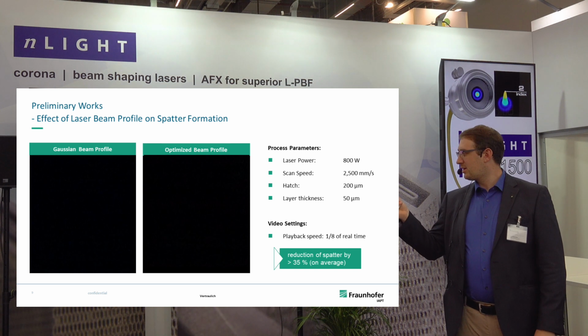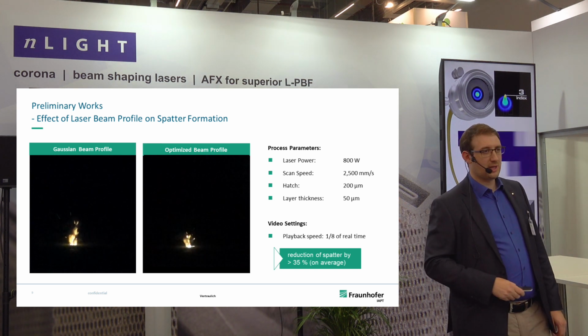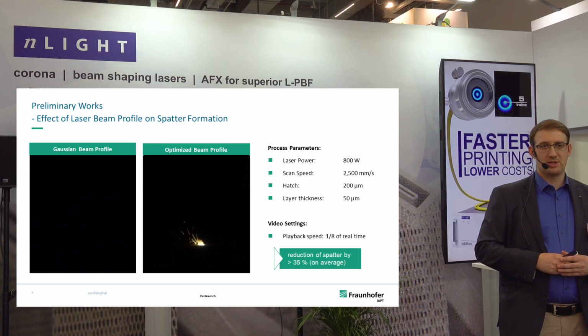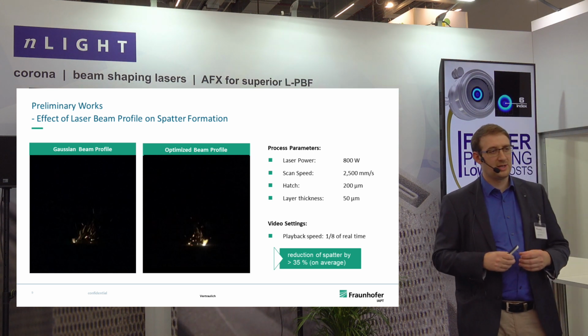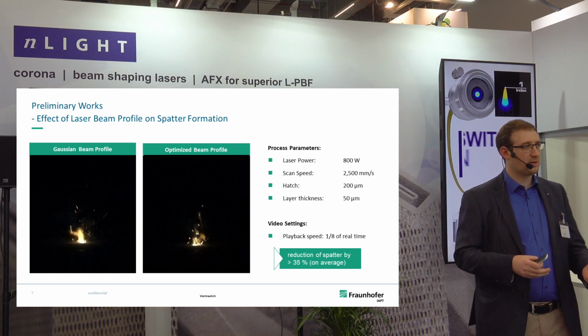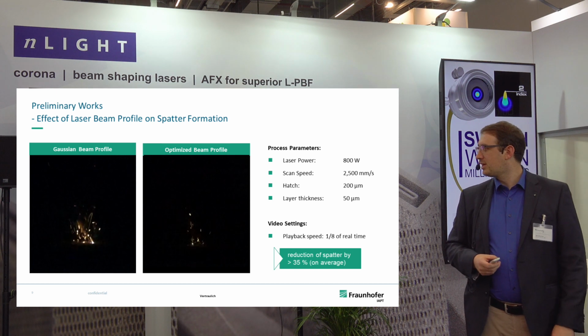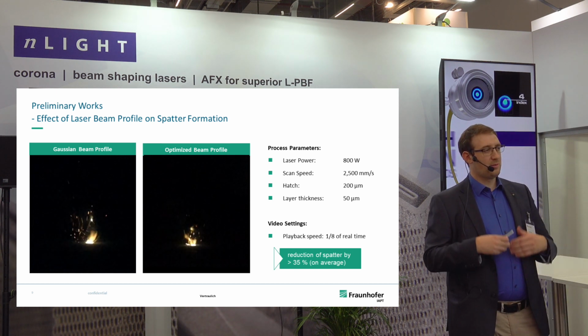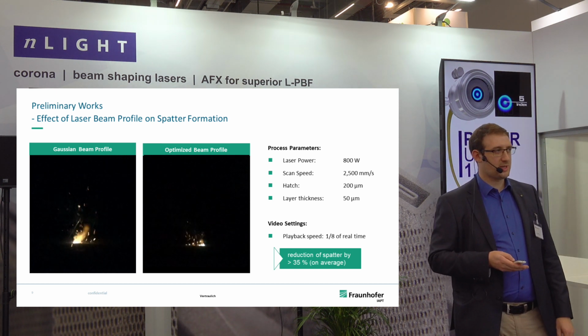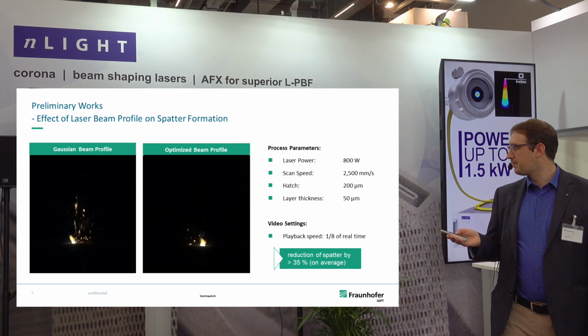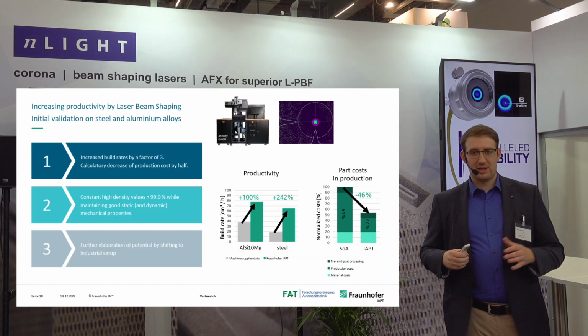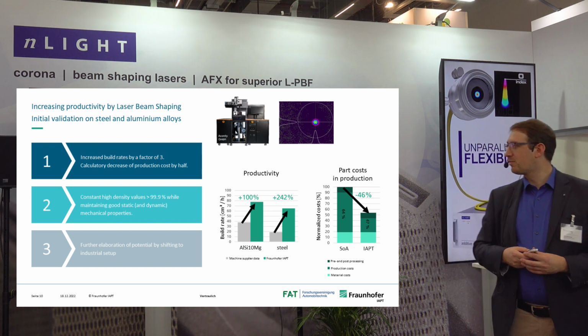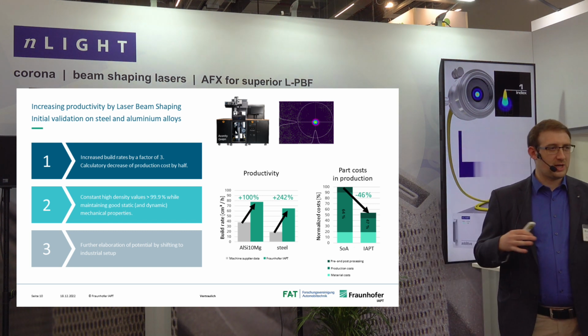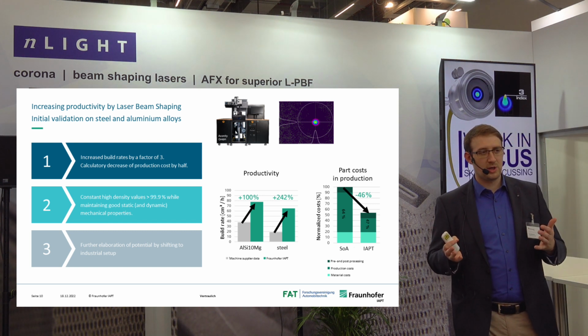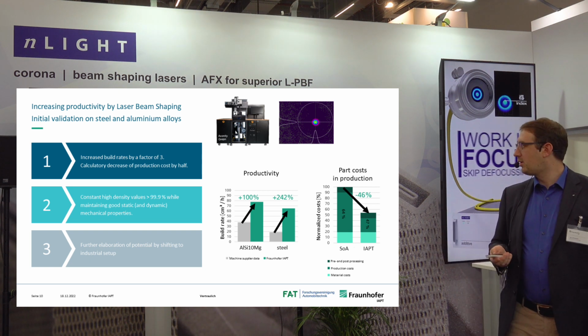So another observation we made is if we're looking at the process, at the byproducts, on the left side you can see the Gaussian profile and the byproducts and the sputter. On the right side, from the donut profile, we reduce the number of byproducts per molten volume. With this in mind, we looked: okay, for AlSi10Mg or aluminum alloys that worked, what about a steel alloy?